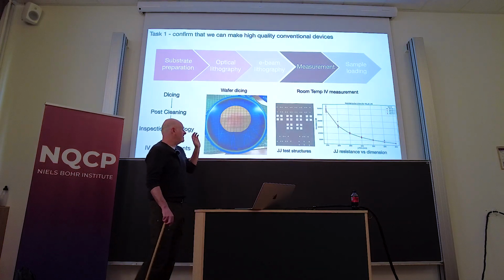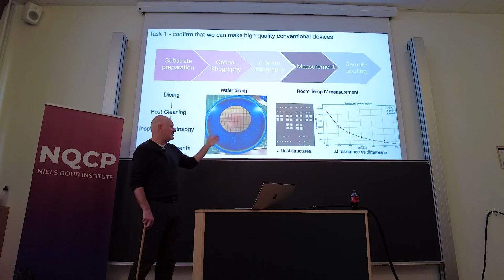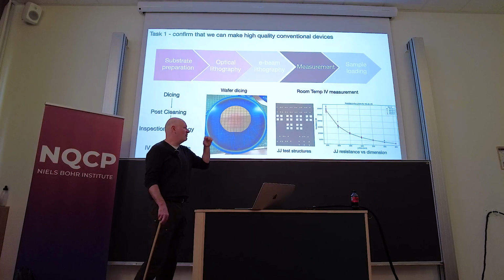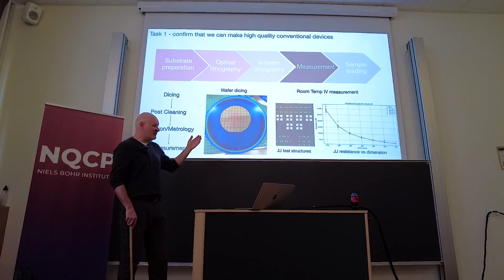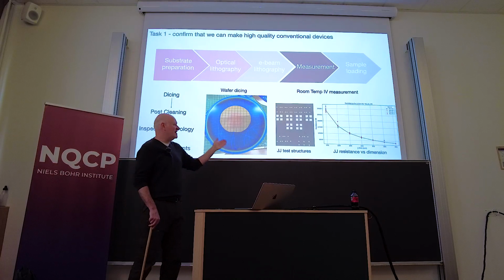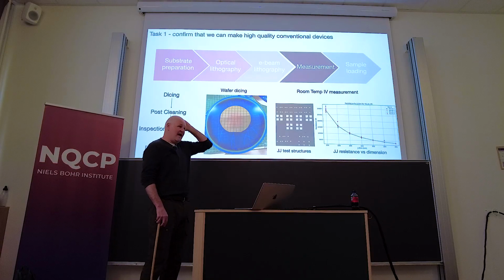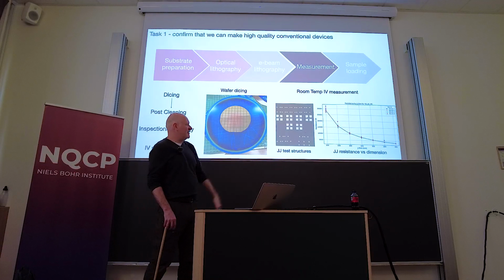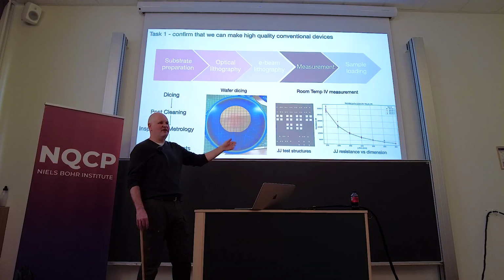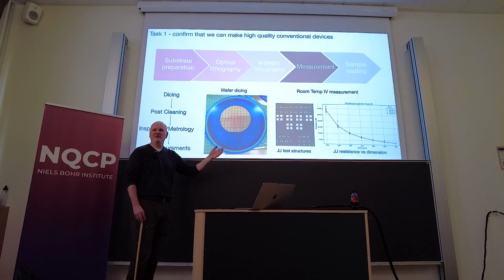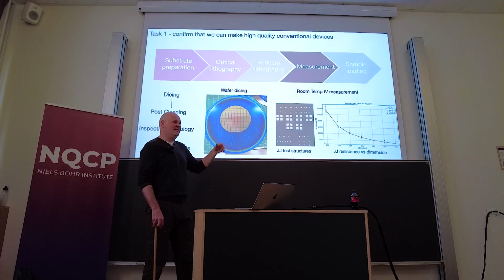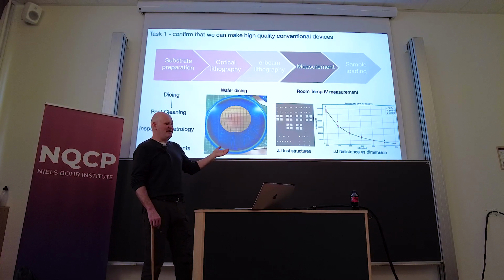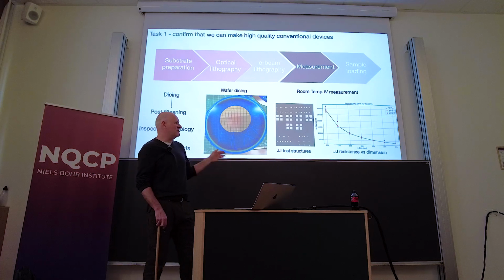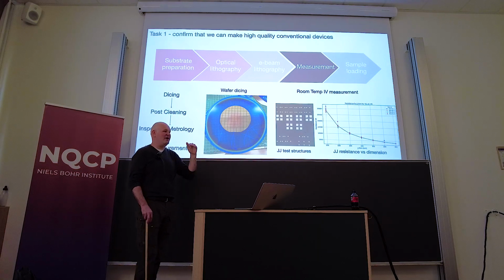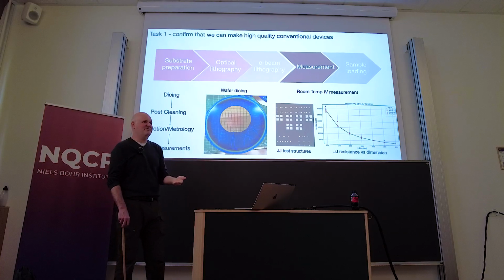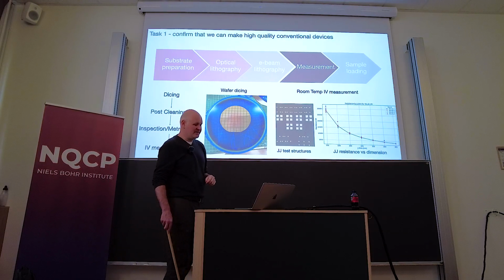Then we do wafer dicing, and then test our JJ test structures. So we made a whole wafer full of Josephson junctions, several wafers of Josephson junctions, and then test the resistance versus the dimension. And we're showing one figure here, but this was 6 months of work of trying to optimize the oxidation step in the Josephson junction fabrication. Because every tool is a little different, we really had to optimize our JJ fab tool to make sure that our oxides were the right thickness, so that we get the right resistance, so that our final devices would have the right frequencies.